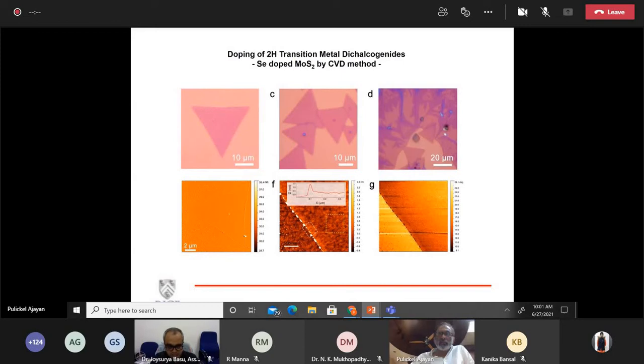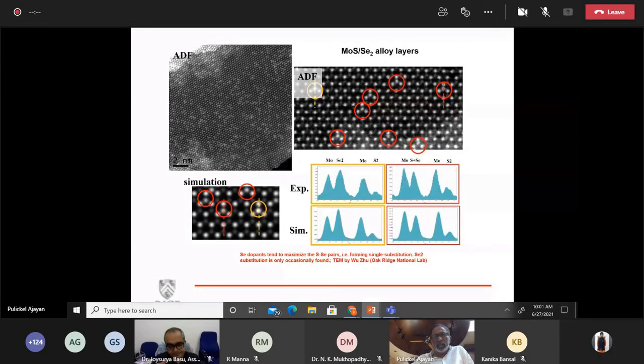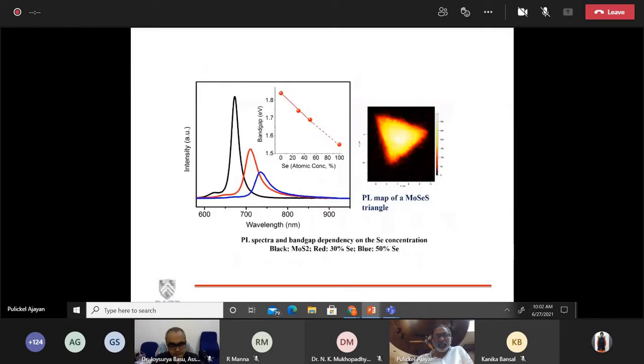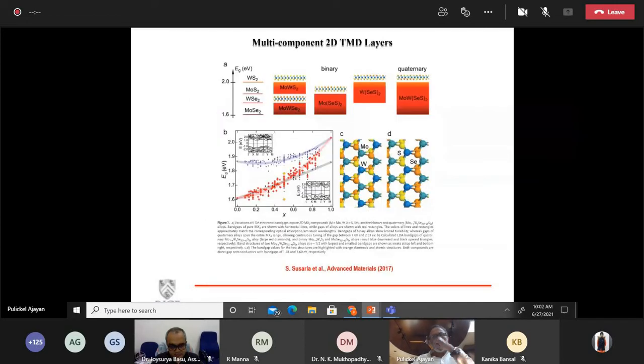Now, doping, of course, is also a possibility on large areas of these 2D layers. And we have, again, worked on doping with elements that are similar. For example, you can dope molybdenum sulfide with selenium or tellurium. You can dope molybdenum sulfide with tungsten. And that can lead to pretty good alloys of these elements, 3-component or even higher component. And that changes the electronic structure. And you can tailor the electronic properties by changing the concentration of the dopants. And it's also been seen that going from 2-component to multi-component, you get a higher band gap tunability.